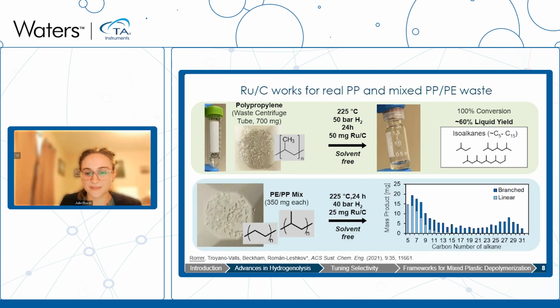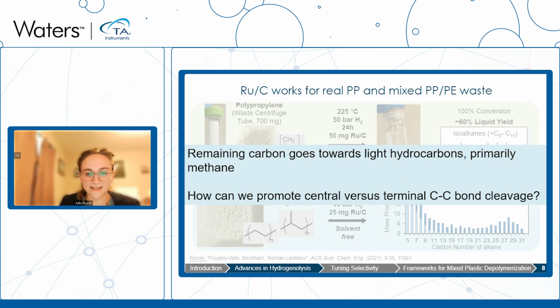But of course, when we think about real plastics, they're often going to be mixed together with all sorts of different types of materials. And so as a proof of concept, we took a mixture of both polyethylene and polypropylene and deconstructed it using our catalytic system into a mixture of branched and linear alkanes, where the linear alkanes come from cleaving apart the carbon-carbon bonds in the polyethylene, and the branched alkanes come from cleaving apart the carbon-carbon bonds in the polypropylene.